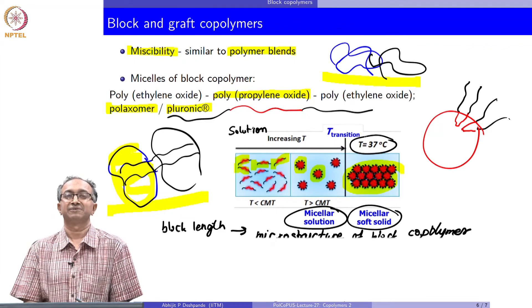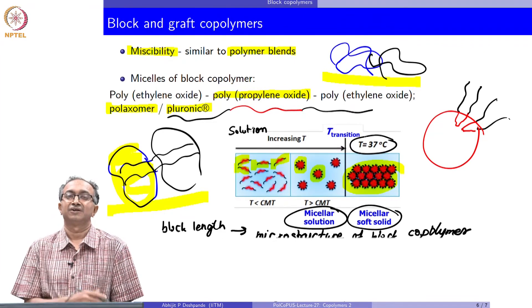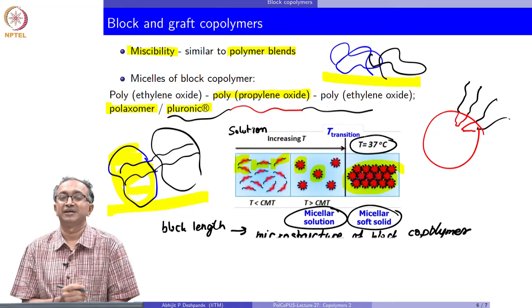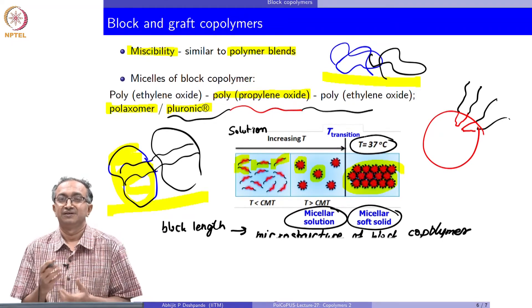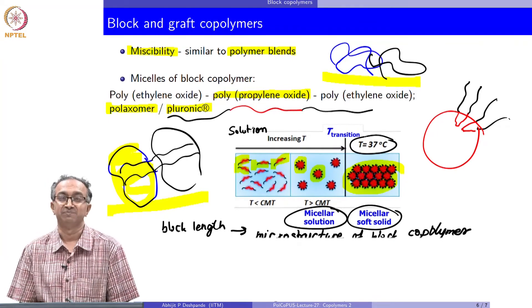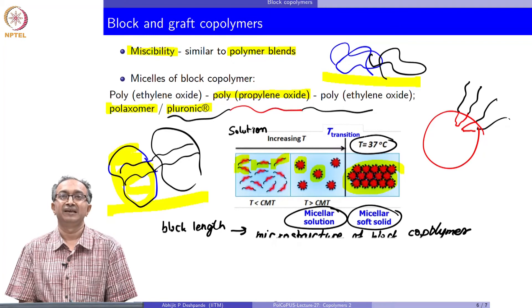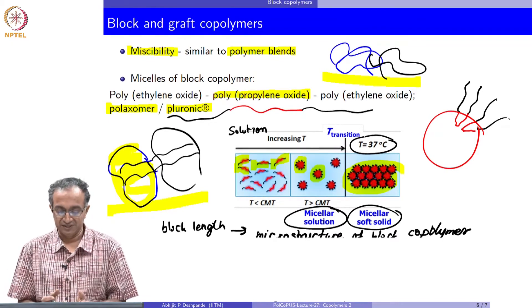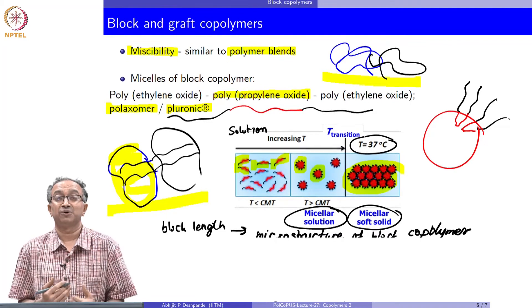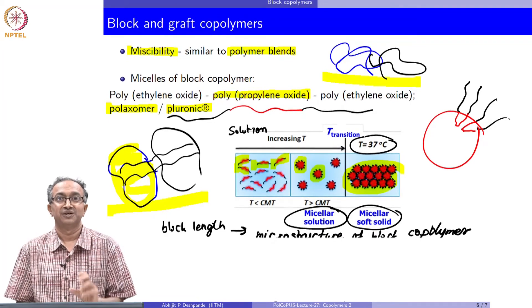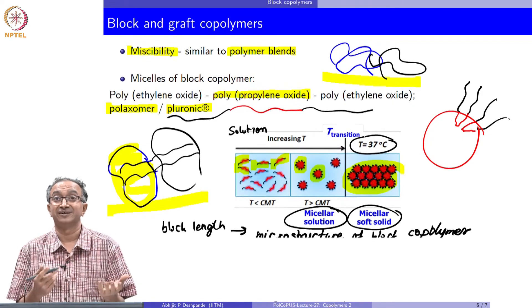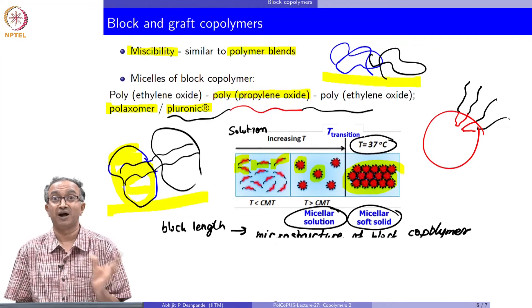Note the temperature here — 37 degrees Celsius. Our body temperature is just above this. So if we tune this transition point well, the material is in solution when stored under refrigerated conditions, and transitions to another state as soon as it reaches body temperature. These block copolymer systems can become a gel when injected into the body at 37 degrees Celsius, but remain in a perfectly liquid state beforehand, so they can be injected easily.